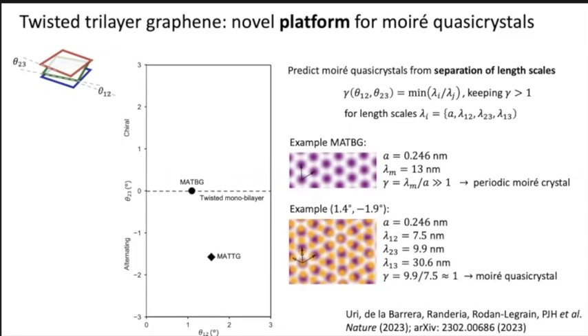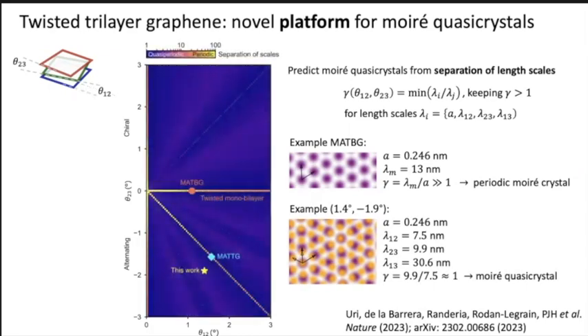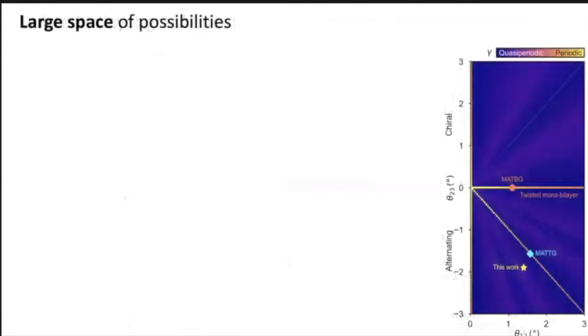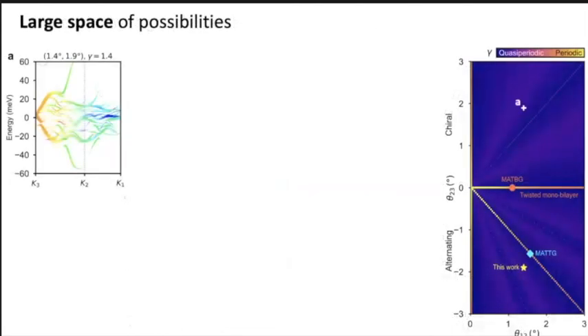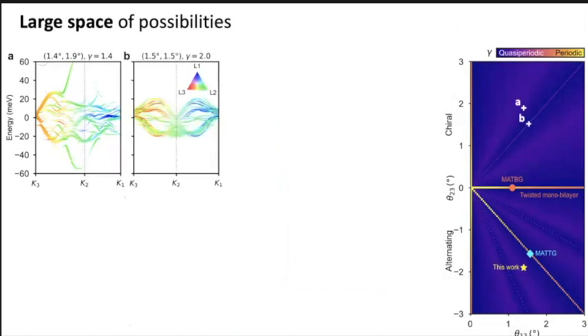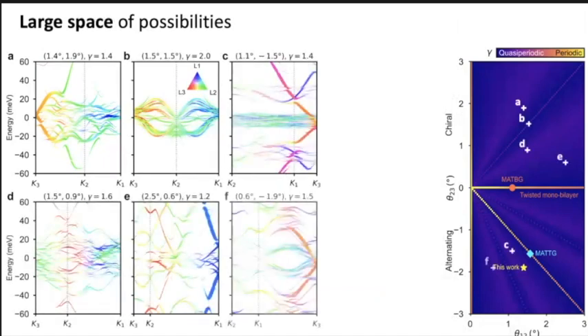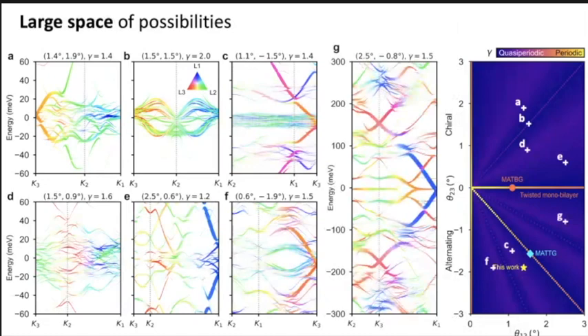So if you look here at when you are going to get a Moiré periodic crystal or a Moiré quasi crystal, it turns out that purple, which is close to one for gamma, is Moiré quasi crystal. Most of the phase space is actually spanned by Moiré quasi crystals rather than Moiré crystals like here, magic angle bilayer or trilayer around this direction, okay? So you can look at the spectral function at point A there, B there, C, D, E, F, G, various points. All of these have different spectral functions with different distributions of flat bands and different topological properties actually, okay?